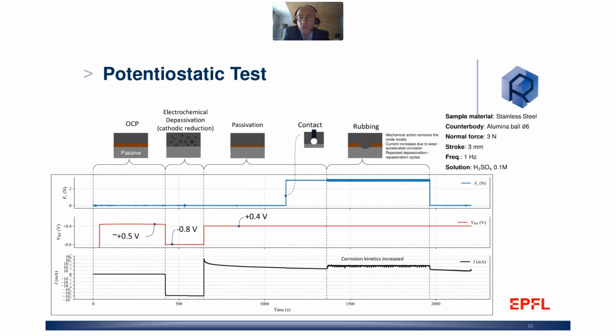But of course, if you start a tribological test, you are able to measure the corrosion kinetics, and then have useful information on either the wear and coefficient of friction of the material under applied potential, as well as measuring a current of the corrosion kinetics with this kind of setup.